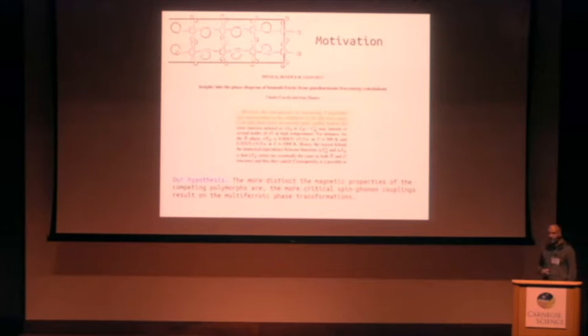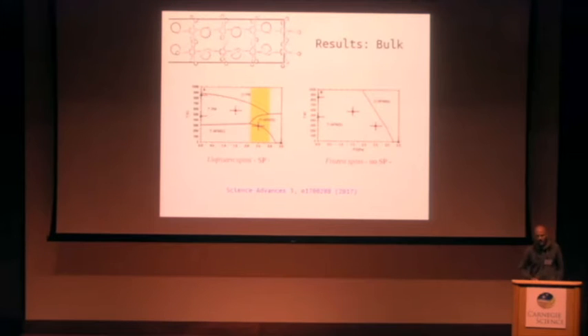And we found out that actually the spin-phonon couplings didn't have any effect really on that transition, right? So we were a bit disappointed, but then we started analyzing in more detail, and we realized that in fact, if you don't look at the phase transition, you just look at the effect of the spin-phonon couplings on each of the free energies. So by using this approach based on DFT, which allows us to take into consideration the effects of magnetic disorder as induced by temperature on the phonon frequencies, we came up with this phase diagram here, right?